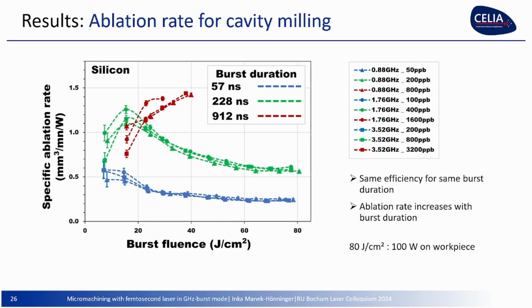I guess there will be some limits. If you even increase the rep rate and then the pulse energy is almost diminished by a factor of 2, well, at a point it will stop. But here you can see that gives the same thing. So it's really the burst duration, which is the key parameter, that will decide what will be the result. And you see, you always have an optimum of the specific ablation rate. So the optimum is related to the burst duration. Same duration gives same efficiency, and it increases because this is 57 nanoseconds, this is 228 nanoseconds, and the red one is 912 nanoseconds. So it's increasing with the burst duration.